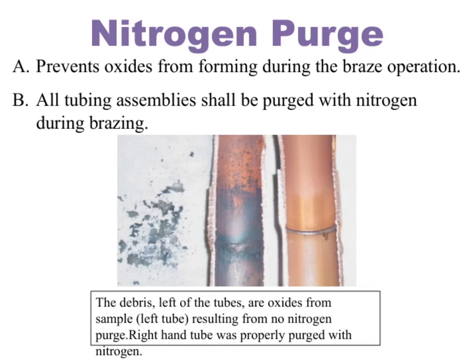Let's take a closer look at nitrogen purge. On the left side, you can see the debris. These are oxides that formed on the sample left tube. This happened because there was no nitrogen purge during the process. Oxide formation is a common issue when metals are exposed to air at high temperatures, which can compromise the quality of the brazing. Now, on the right side, you see the right tube that was properly purged with nitrogen.